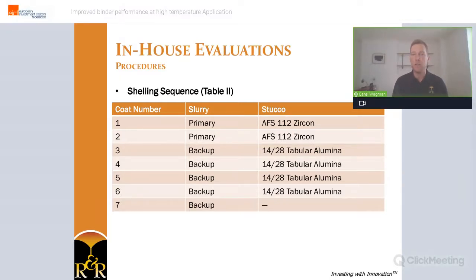The shelling sequence was the same for both with zircon and with tabular alumina stucco. Intercoat dry time was kept at 2.5 hours under a moderate airflow and ambient temperature of about 24 degrees C. All stucco application was done by rainfall sanding.